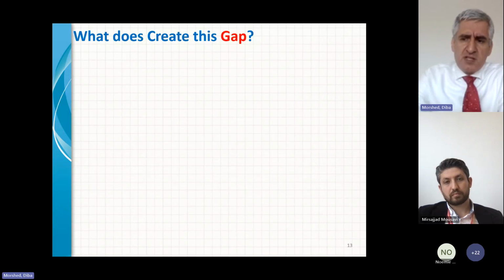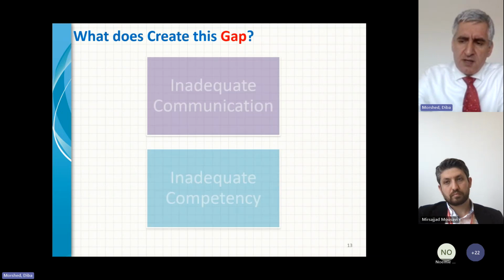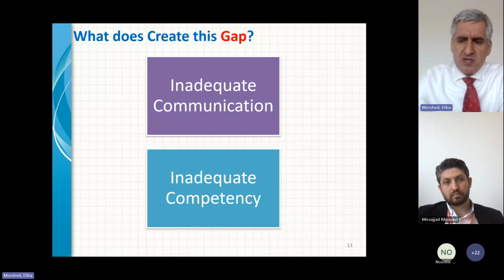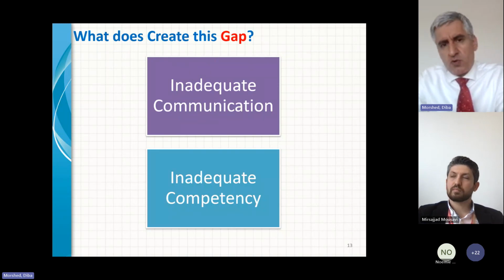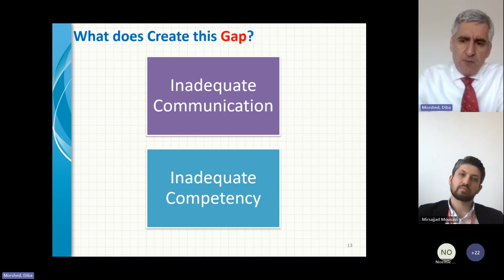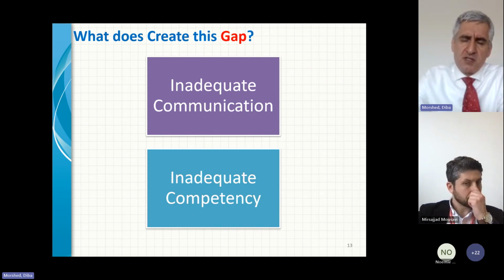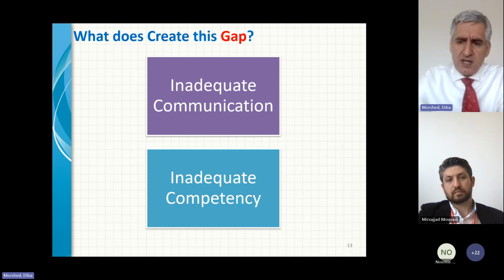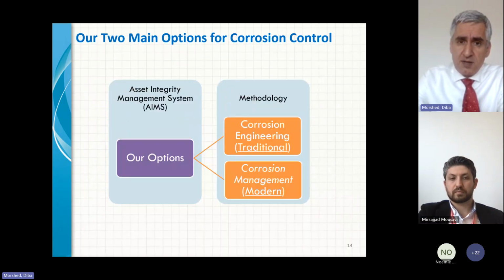So, what does create this gap? If I want to be both precise and concise here, in summary, I can say in 99% of the cases that I've been studying corrosion issues and corrosion failures, two root causes or two culprits have always stood out. The first one has been inadequate communication. The second one has been inadequate competency. So, in other words, if you tackle competency and communication, if you try to improve these two items, you will see significant improvements in your corrosion control and mitigation systems. You would see that your corrosion control system would function with much greater efficiency and performance.